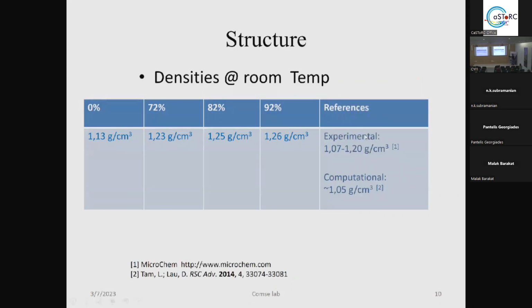You see a range of values, and the reason is that, and this is the difficult problem with these systems, because we're talking about a family of resins, it's difficult to find exactly the same epoxy resin with the same hardener at the same cross-link degree in the experimental table, and to validate it. That's why you see a range of values here, and it is the same problem in the rest of the properties. That's why I have a range of experimental values all the time. But happily, as the cross-linking degree increases, the density increases, and the values are very close.